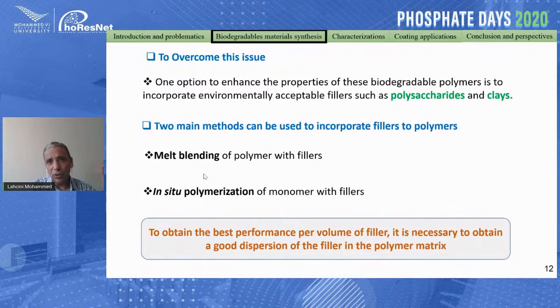For that, it was reported that incorporation of fillers like polysaccharide or clay with the polymer increases their thermal properties, their mechanical properties, and also their barrier properties. But to improve these properties, we should have a really homogeneous dispersion of fillers inside the polymer. There are two main methods to incorporate the nanofillers with the polymer. Melt blending of polymer with fillers is a really simple method. We melt the polymer, we add the fillers, we mix, and that's it, we have our nanocomposites. Or we mix the monomer, catalyst, and fillers, and we grow the polymer inside with the fillers.